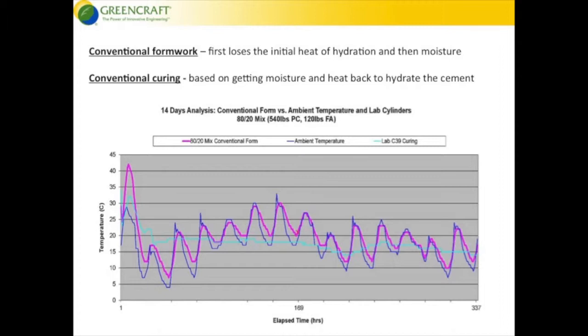So what you're going to see here is that in the first 12 hours or so, a conventional concrete form is going to raise the heat of hydration and reach a peak temperature, generally in the evening, before midnight or so, provided you pour the concrete sometime before noon. And then immediately, as you're losing this heat to the environment, it's going to drop, so that by the next morning you come to have ambient temperature. And from that point on, pretty much conventional form concrete is going to track the daily temperature fluctuation of the environment for the rest of that structure.